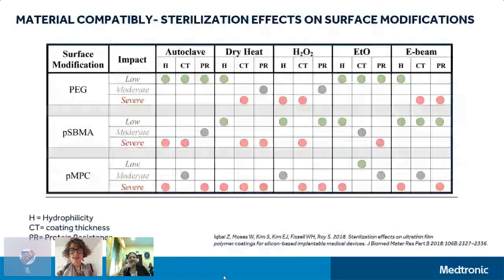Most of the medical devices we use have some kind of surface modification for adding functionality or improving performance. So this research looks at very thin polymeric coatings on silicon substrate and subjects them to different sterilization technologies, assessing the hydrophilicity, looking at whether there is an adhesion issue, or whether in general the coating has deteriorated and if the protein resistance has also deteriorated. And as you can see here,